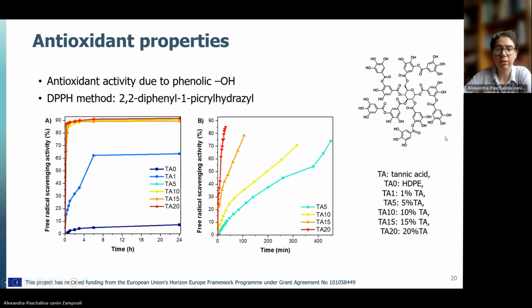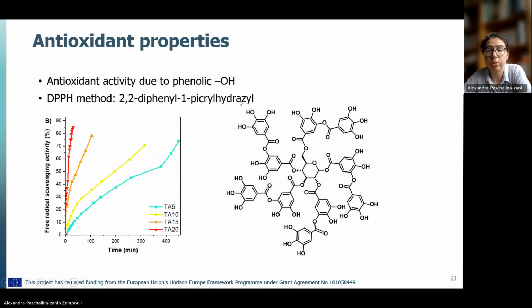So we did a second set of experiments with more frequent measurements. And you can see that the materials exhibit exceptional antioxidant properties, with the material with the highest tannic acid content scavenging 85% of the radicals in 30 to 45 minutes. This antioxidant activity is due to all these phenolic hydroxyl groups that are free and have not been affected by the preparation of the composite.